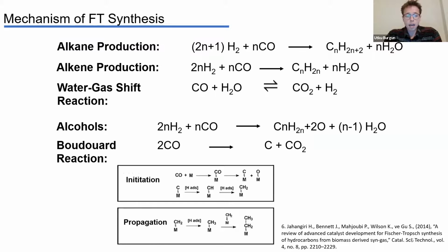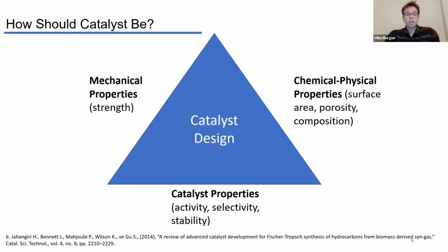If we talk about the mechanism of FT synthesis, the reactant gases in appropriate composition react over the catalyst to produce alkane, alkene, and alcohols, and at the same time, the water gas shift reaction and Boudouard reaction occur here. Here, the carbon monoxide molecule first dissociates on the active metal of the catalyst, and the first CH intermediate occurs with the addition of hydrogen. And with the continuation of the addition of the reactant gases, chain growth occurs, and the products start to be produced. How should catalysts be?